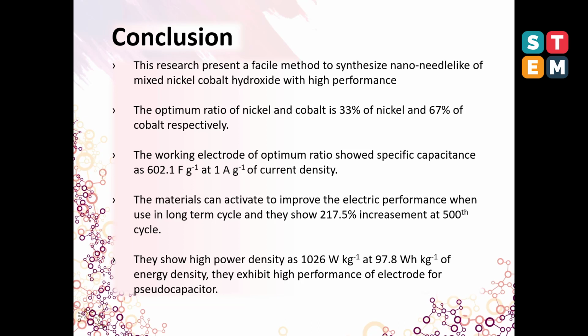The working electrode of the optimum ratio shows high specific capacitance, and the material can activate to improve the electric performance when used in long cycles. Moreover, the electrode shows high power density and energy density for pseudocapacitor application.